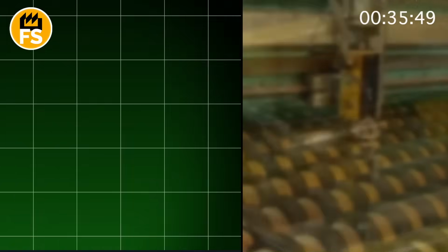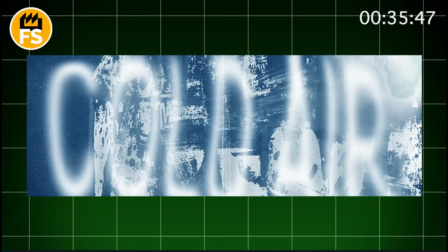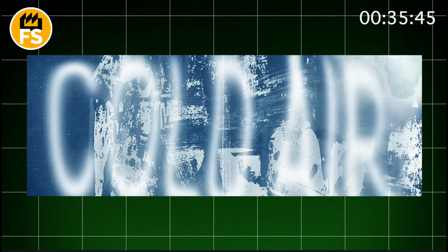The red-hot, softened sheet of glass rolls out of the hellish maw of the furnace and is immediately ambushed. From all sides, top and bottom, a barrage of cold air under high pressure hits it. This process is known as quenching, or tempering. Dozens of powerful nozzles with a deafening roar blast the glass surface. This sudden, extreme cooling is the key to the whole process.